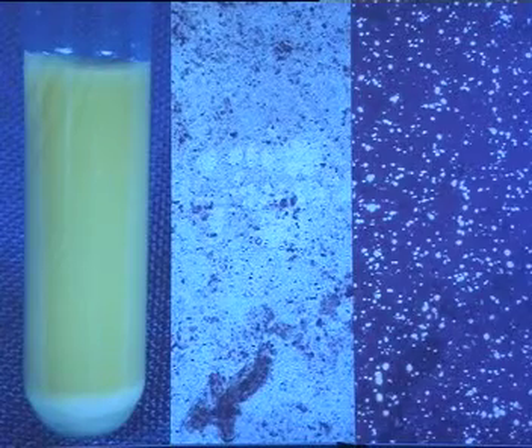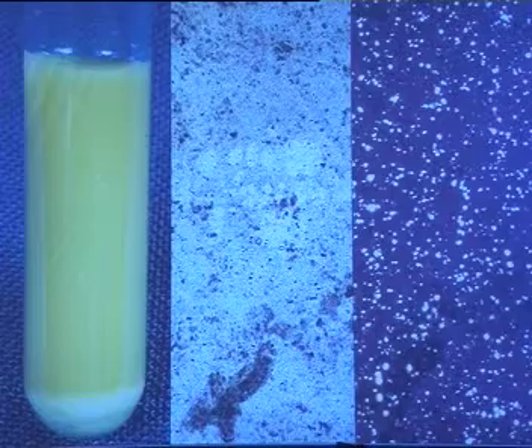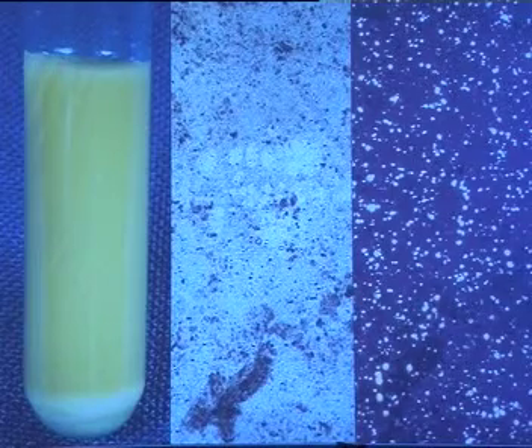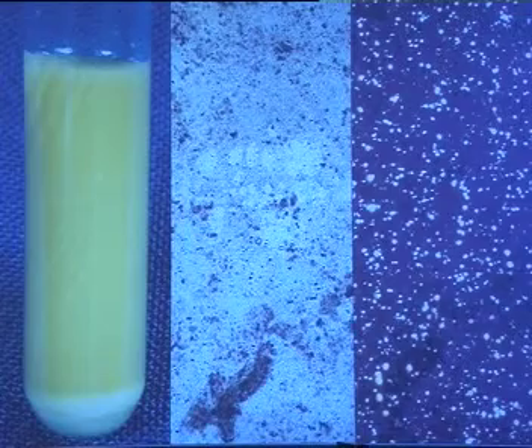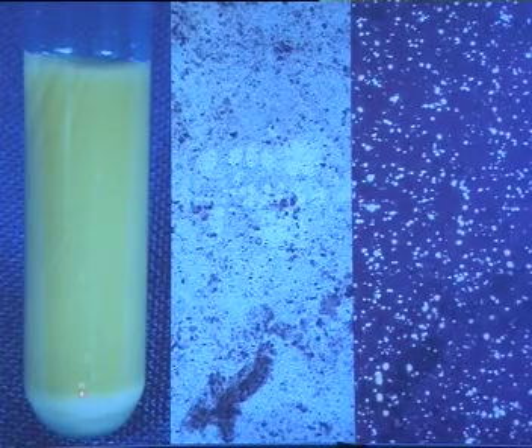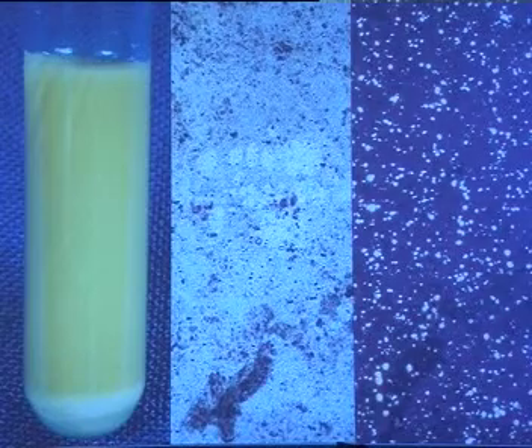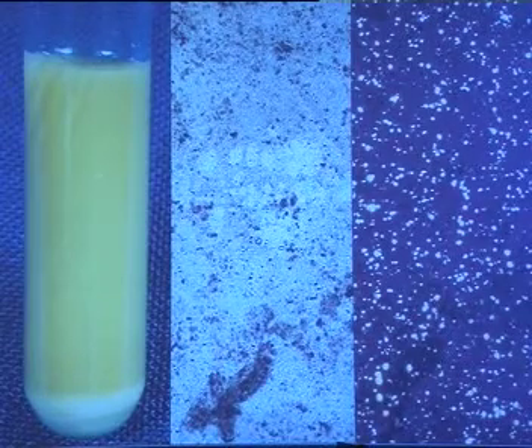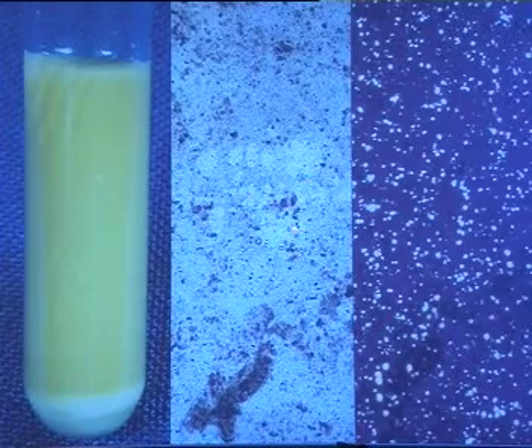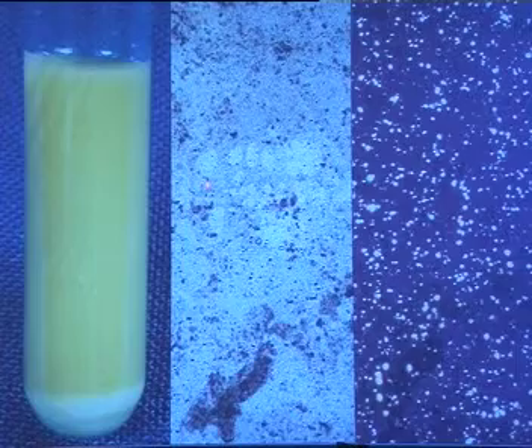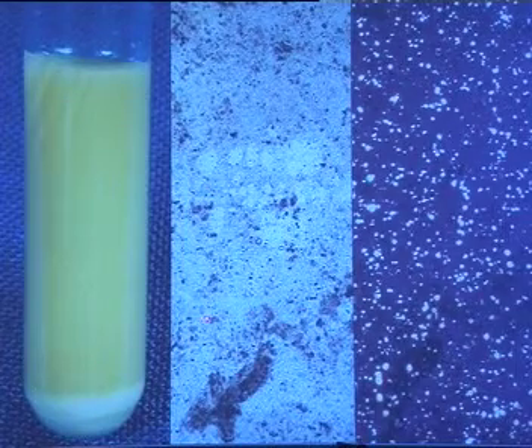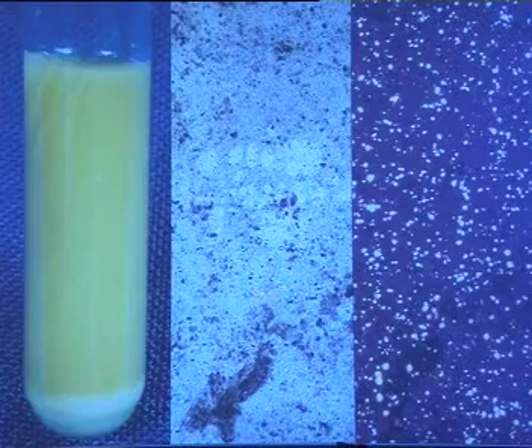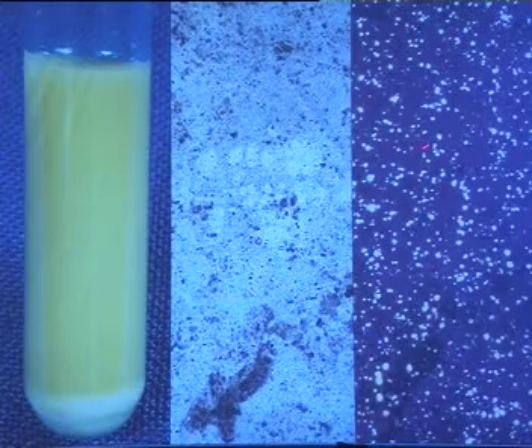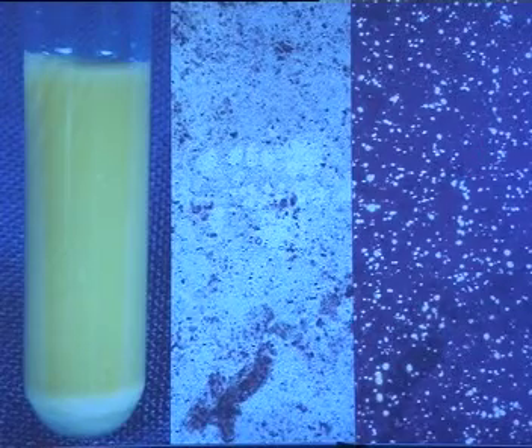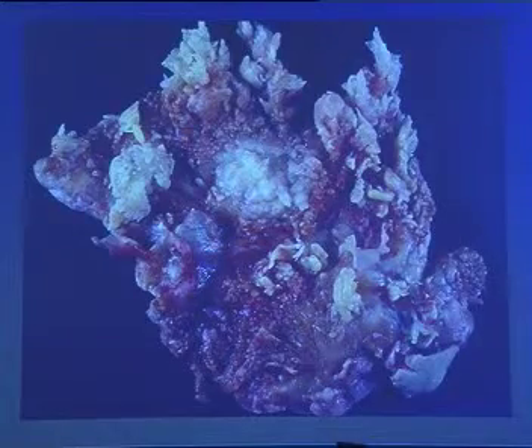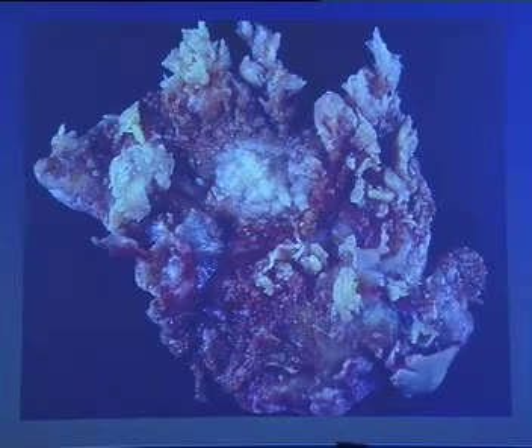So, as a surgeon, the patient comes to you, your colleague, the rheumatologist or the clinician says that there is a swollen knee. What do we do? So they go in, they aspirate this, and you see this turbid fluid, and you think, is this infection or is this polyethylene debris? So we as pathologists then spin it, and we put a drop on a glass slide, and here we see this muck, if you will, and this certainly does not look like infection. It's not polymorphonuclear, or it's not chronic inflammation, and when you polarize it, you see that it's in fact all implant debris, confirming that it was implant material and not infection, and thereby we help you to decide what to do next.